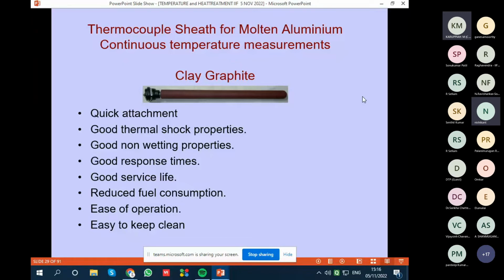Only precaution you have to take is to take the thermocouple out of the molten bath before the furnace is put off. You should not leave the thermocouple in the bath when it is getting cooled down, otherwise this will break. This is very economic, 5,000 rupees or something like that. And these are used with proper precaution. You can use it for about 50 to 100 cycles, and then you can just replace the sheath and start using it again. This is very popular in most of the aluminum foundries today.